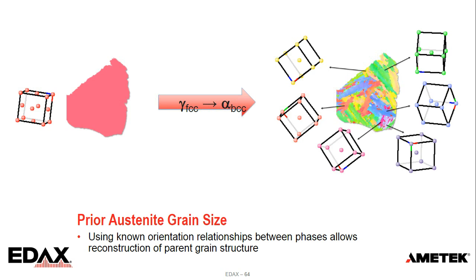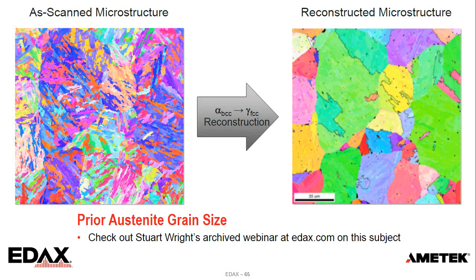But essentially what's happening is we start with our austenitic FCC phase at higher temperatures there on the left. And as it transforms through the transition temperature, there are different possible orientation relationships between the FCC austenite and the BCC ferrite. So it can transform by certain rules, with tolerances. But if we know those and we put those into the software and we do some permutations, we can reconstruct the microstructure. And that's an example here, going from the as-scanned microstructure to the reconstructed microstructure on the right.